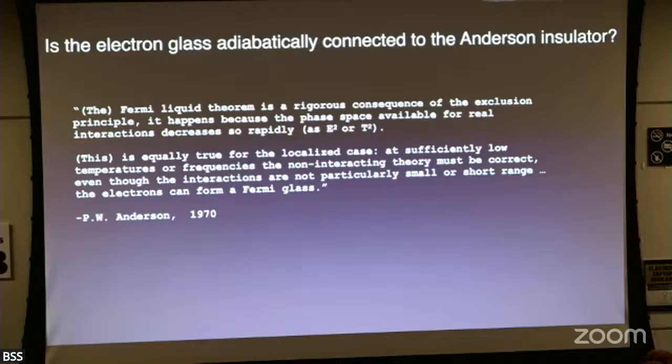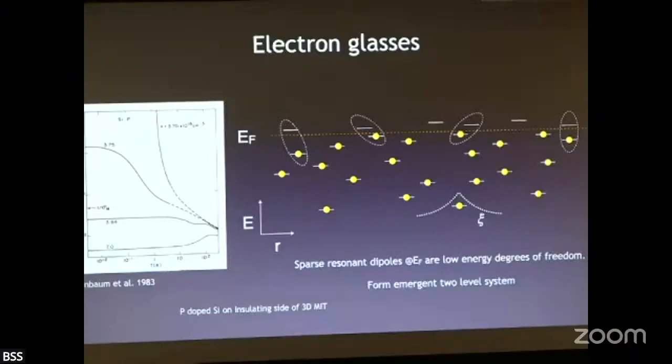Yeah, so what happens is there's a very small chance that it could get ionized, putting an electron on a donor. Once you start getting enough of them, there starts to be overlap of the wave functions, and now you get clusters. And some of those clusters ionize. There are some clusters, just through rare events that we've heard about, rare regions, for which it becomes energetically favorable to accept an electron from another cluster, and that opens up space. So that's generally what's considered to happen.